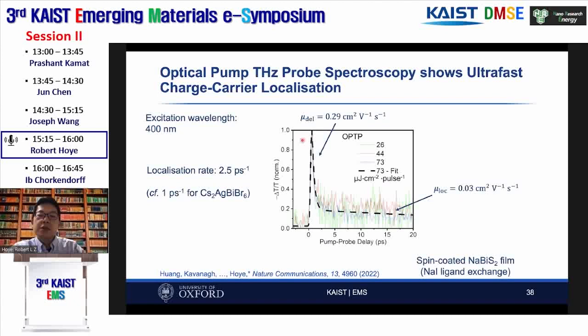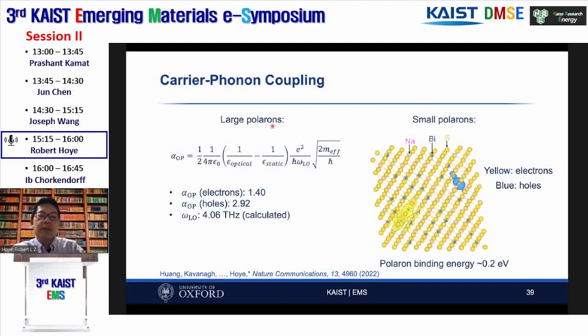So this rapid localization is too fast to be due to trapping by defects. It's much more likely to be due to a process called carrier localization, which is when charge carriers couple to the phonons in the lattice to form localized states. In other words, the electron wave function is localized within a unit cell. And then in order for these charge carriers to move, they have to move by hopping between different states. This can happen if you have very strong coupling towards large optical phonons, or you have coupling towards acoustic phonons.